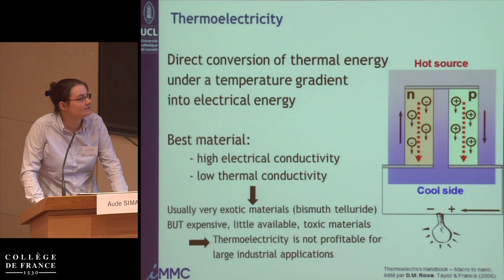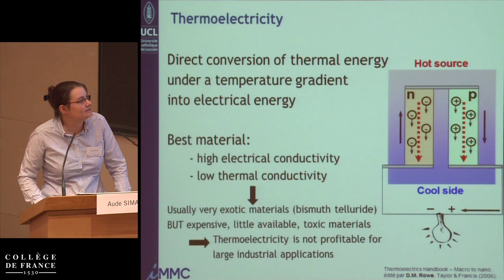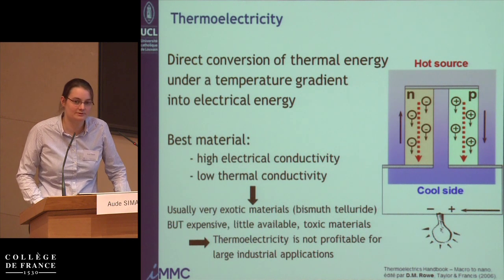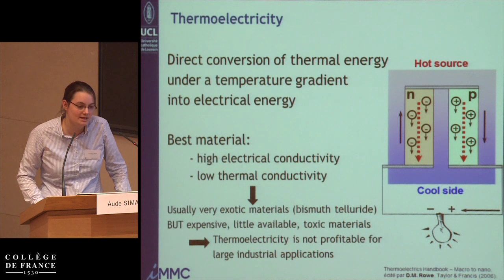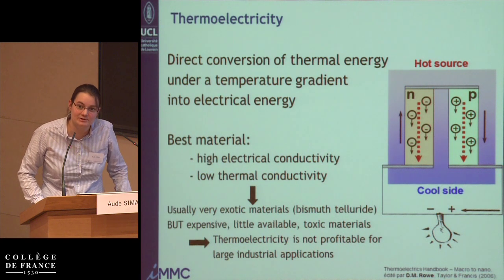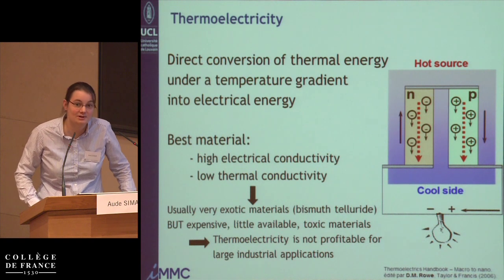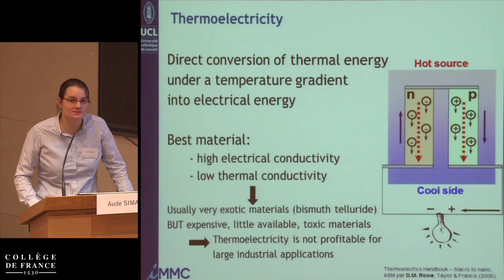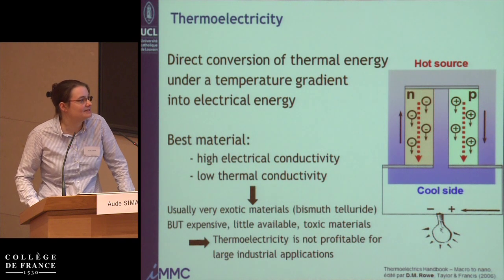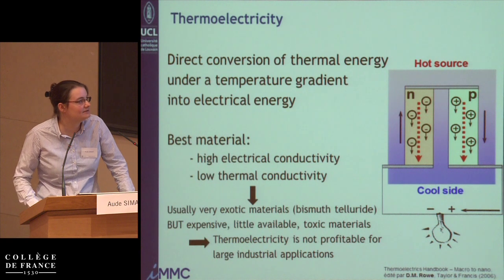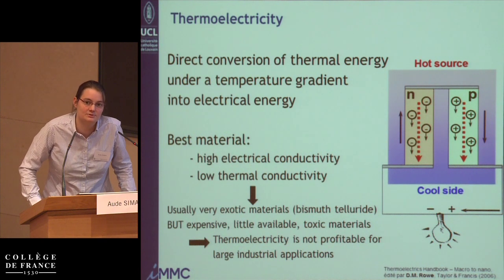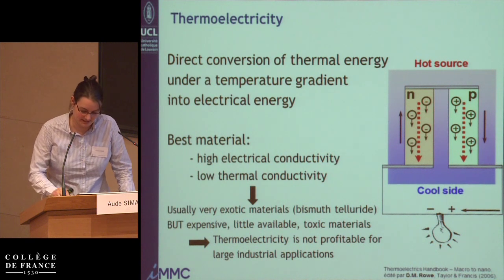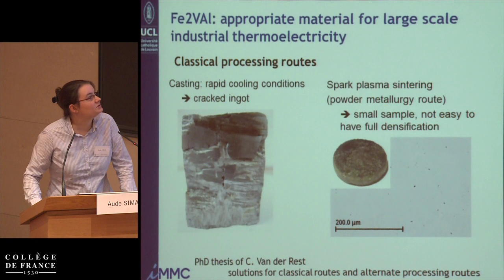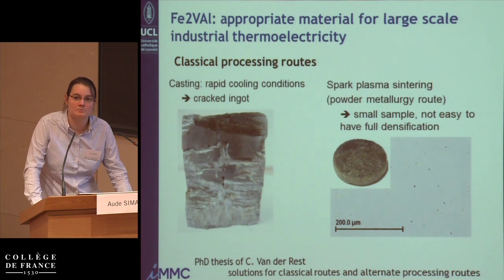And what's interesting here is that if you have a material that has a high electrical conductivity and a low thermal conductivity, which is of course not very easy to reach, because usually, well, we are talking about copper. Well, this is definitely not the case of copper. So you see that we are talking about very exotic materials, bismuth telluride, expensive, little available, toxic materials. And so thermoelectricity is not profitable for large industrial application usually, because we are talking about materials that are very little available and expensive.